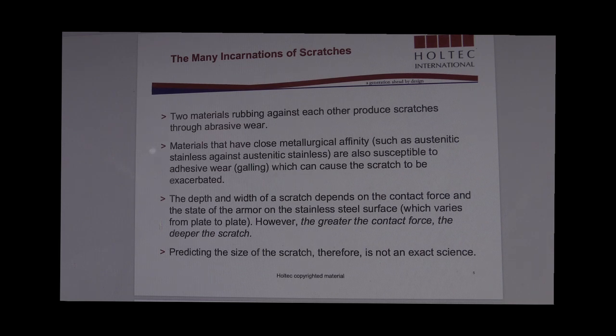The other phenomenon in play here is adhesive wear. This can occur when the materials are compatible or have similar metallurgy, such as austenitic stainless steel, where you have a bonding of the material and a transference of the material across the two interfacing surfaces. So it can deposit material on one surface and remove material from the other surface. So there's a combination of effects here, both abrasive wear and adhesive wear, that we observe both in the manufacturing space and in the field as well.